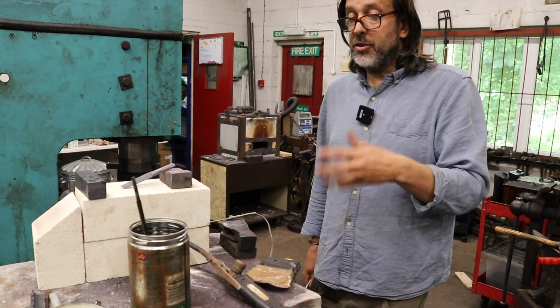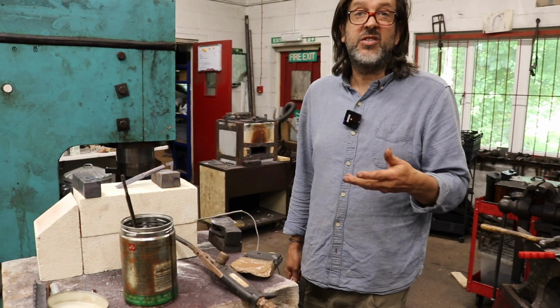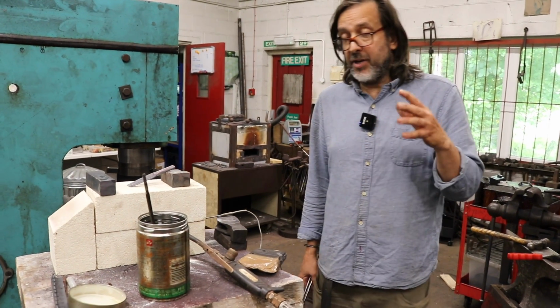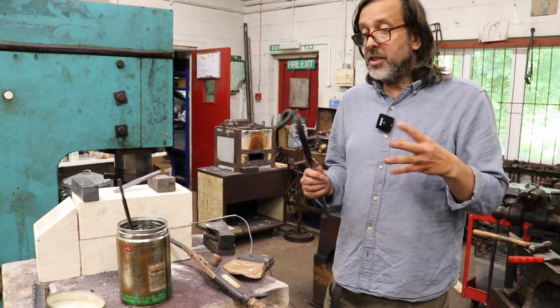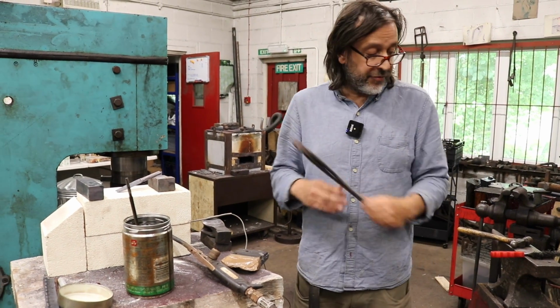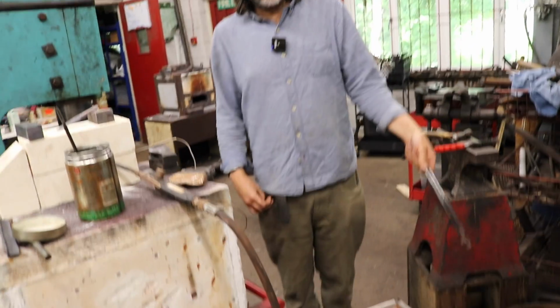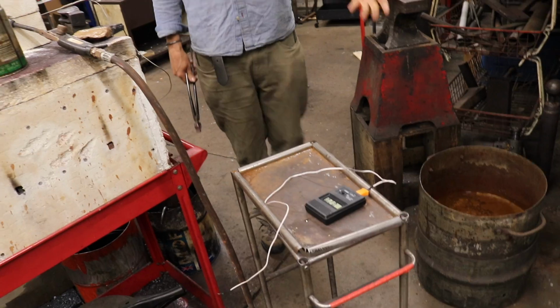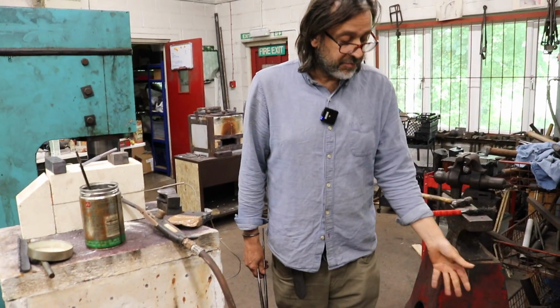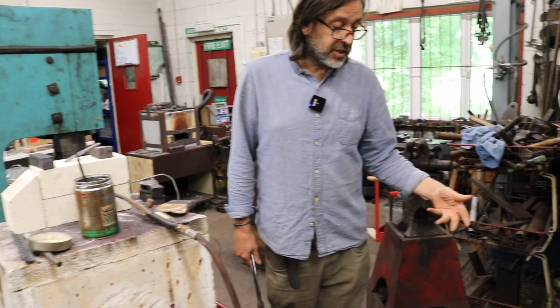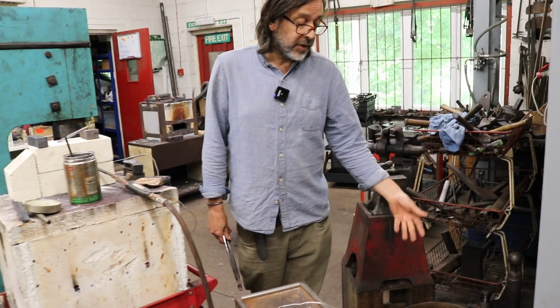You do get some steels which are water hardening, but they're not so common now. And generally a quick oil is better. But in terms of speed of hardening, if you were to harden in water, that will pull the heat out or cool it quickest. So that will give the quickest hardening.